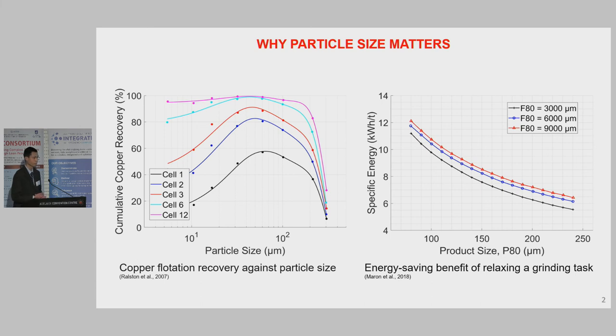As can be seen from the figure on the left side, for maximum flotation recovery, the particle size is required to be neither too small nor too big. That's useful from the perspective of comminution. Looking at the figure on the right side, we can see huge energy consumption when particles are ground to very fine grains. So if we can reduce the grinding task by grinding only to the optimal particle size required by flotation, then we'll be looking at some points around the right side of the curves, which are associated with much less energy consumption.